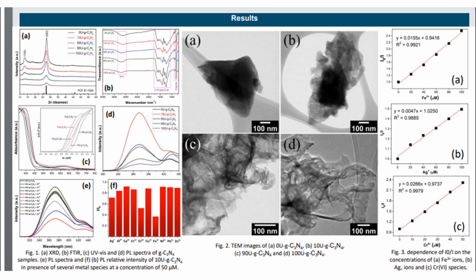The 10% urea sample was used to evaluate several metal species at a concentration of 50 micromolar. The PL spectra show significant changes in the maximum emission of graphitic carbon nitride in the presence of different metal species. According to these results, the semiconductor shows good selectivity for iron 3 and silver ions, as well as for the chromium 6 species, whereas the other metal ions showed little or no quenching effect. As can be noted, there is a decrease in the fluorescence emission of around 37, 50, and 70%.